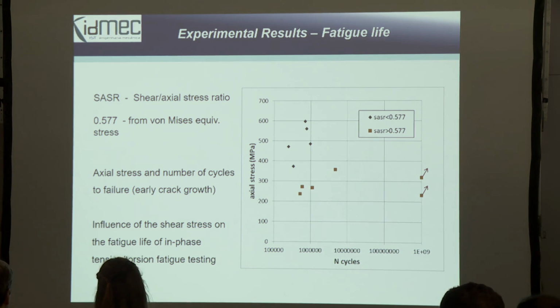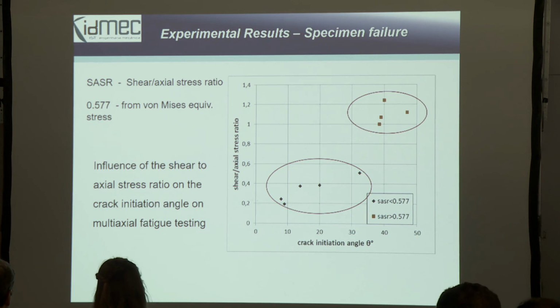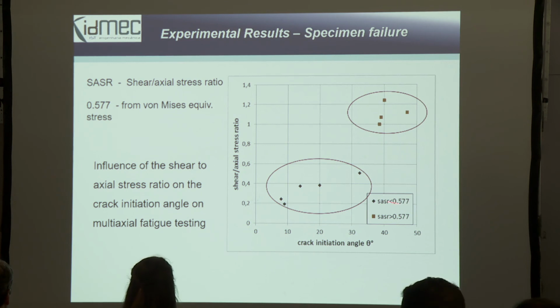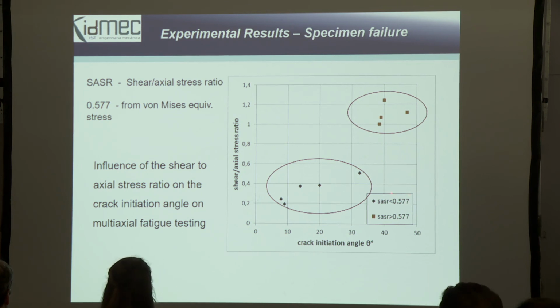And the second one also, the inclination, the calculated angle according to the shear to axial stress ratio, again for higher shear stress than axial, or higher axial than shear stress. So there are two different behaviors. This is absolutely comparable with servo-hydraulic torsion testing machines. So we think we are on the correct solution for having in ultrasonic fatigue testing the three solutions for axial, for cruciform, or for tension torsion.